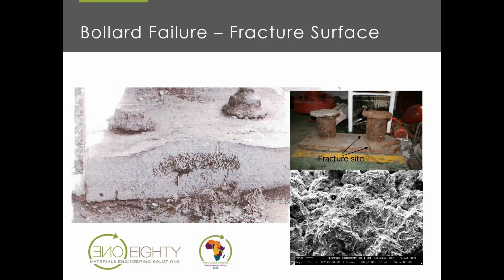But there wasn't. So this was a catastrophic failure that happened on the day, and the fracture surface was entirely metallic. Of course, the expert on the other side said, well, this is a bad image, you can't be 100% sure, and all the rest. But we managed to get around that.